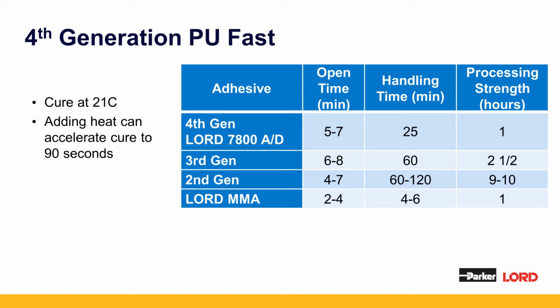You can see here that those 2nd generation and 3rd generation structural polyurethanes take between 9 and 10 hours and 2.5 hours on that processing strength column, whereas the 4th generation structural urethane by Parker Lord is that Lord 7800, takes only 1 hour. And in comparison, the Lord MMA takes also 1 hour. Again, a 2 to 4 minute open time acrylic adhesive. The cure here was done at 21 degrees Celsius, and you can also certainly add heat to any of these adhesives and accelerate them.